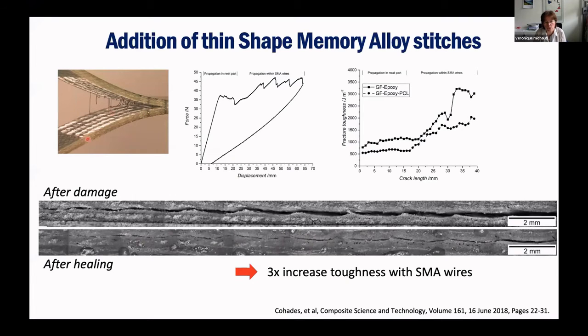And then we see also that we had the SMA just at the end of the sample, and we had a virgin, without SMA zone here. And you see whether you have just a pure epoxy or Epoxy-PCL, you see that the fracture toughness with the Epoxy-PCL indeed is a bit lower, as we knew when you have no SMA phase. But as soon as you go into the region here where you have the SMA wires, we see that we have a big increase in the fracture toughness created, of course, by this.